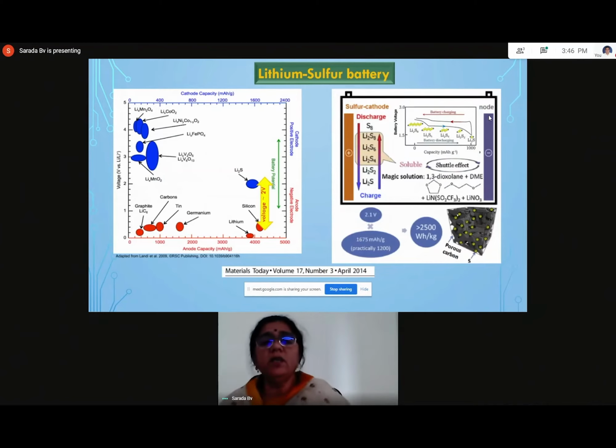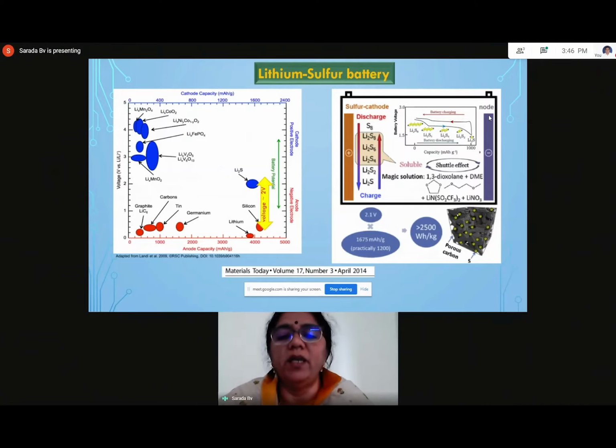Now, why is the lithium-sulfur battery very important? When you are using both anode and cathode as lithium composites, it becomes very expensive, and also the performance is lower. In order to improve the energy density, power density and the power output, we can go for lithium-sulfur batteries, which are of course at research level and soon going to become a technology. You can see over here, the theoretical capacity is 1675 milliamp hour per gram, and the energy density is about 2500 watt hour per kg for lithium-sulfur batteries.